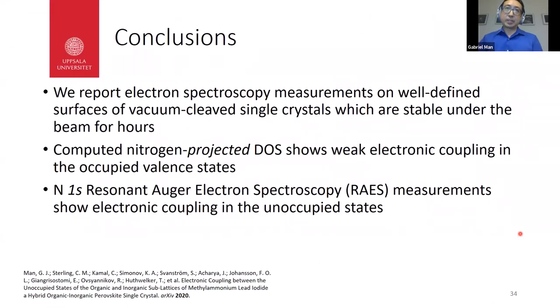So I'm just going to wrap this up with a few conclusions. First, it is possible to perform extended measurements on halide perovskite surfaces, but one needs to take a few precautions. The second is that our computed nitrogen projected DOS shows weak electronic coupling in the occupied states. And the third is that through the use of resonant Auger electron spectroscopy, we can show that there's electronic coupling in the unoccupied states.